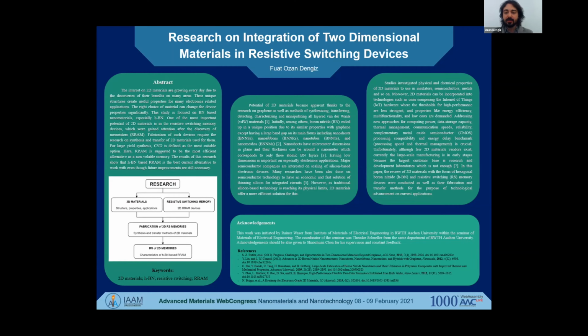And my work is focused mainly on boron nitride with hexagonal structure, or HBN for short. So in this paper, the review of 2D materials with the focus on HBN and resistive switching RS memory devices was conducted. Also, their fabrication and transfer methods for the purpose of technological advancement in current applications are examined. The resistive random access memory, or RRAM for short, seems like the most efficient alternative as a non-volatile memory here. The results of this research show that HBN-based RRAM is the best current alternative to work with. However, as always, future improvements are still expected.